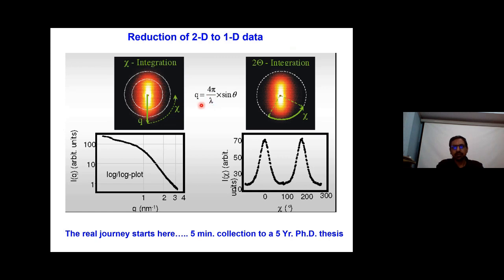And so as a function of Q, which I told you is the scattering vector, which is nothing but related to the angle, where the angle of scattering is 2 theta. This 2D data is actually converted into 1D data, and this is what 1D data looks like. When the operator gives you data, it will be something like this: I of Q versus Q, that is intensity versus Q, or intensity versus theta in simple language. This is what your data looks like. Now, this doesn't make any sense. Your sample might have, for example, spherical nanoparticles or rod-like nanoparticles or surfactant assemblies. But what is this? That is where your real journey starts.